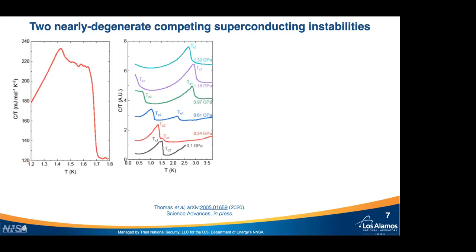This is sample dependent, and again, this is an open question right now, and I hope to get back to this at the end of the talk. But independent of the small variations that are observed, the two peaks are always there. Then we got this sample, or a sample very similar to this, with the clear two peaks, and we applied pressure to it. Here, this is the second plot. We can see TC1, TC2 at low pressures, and then as we apply higher and higher pressures, these two transitions actually cross each other.